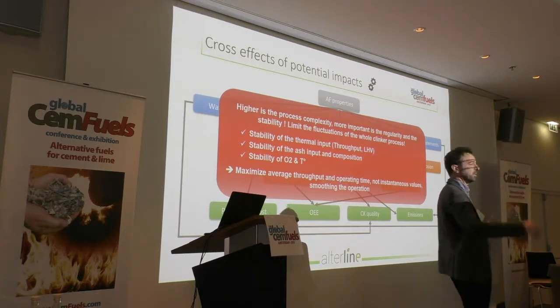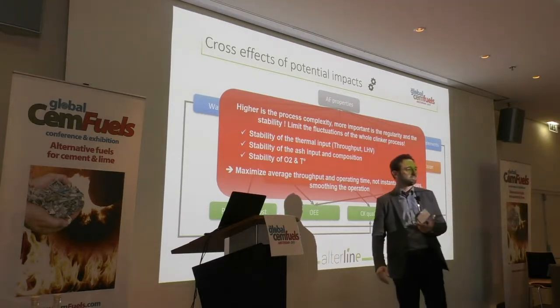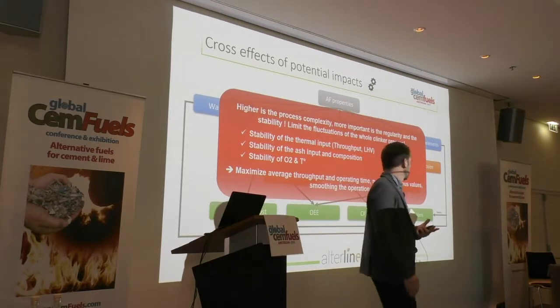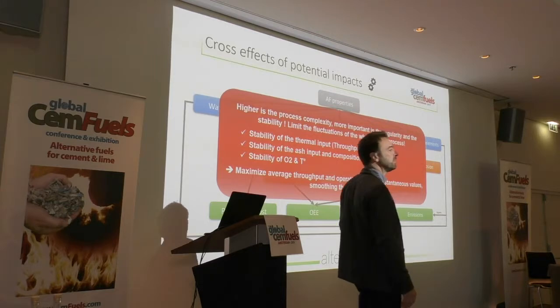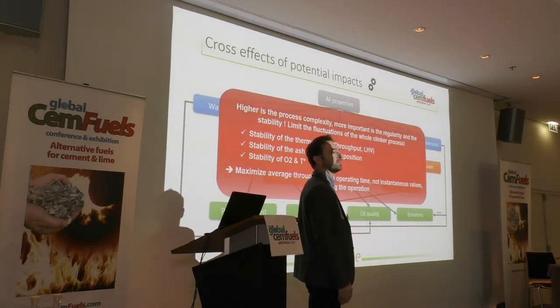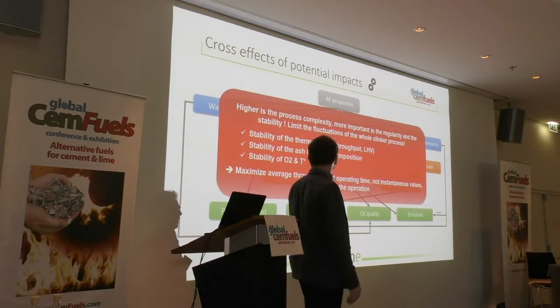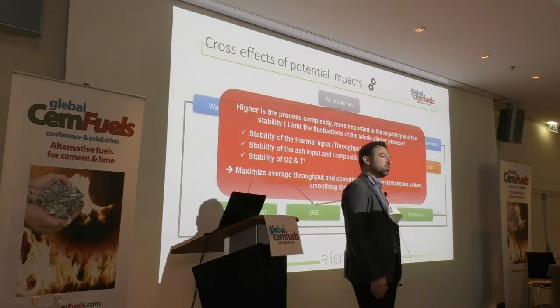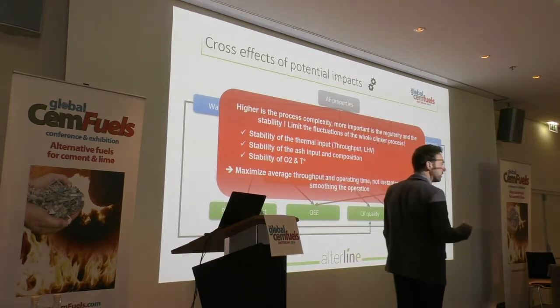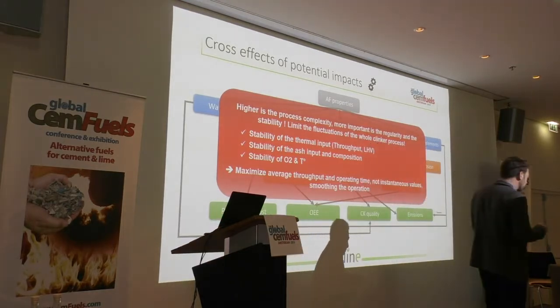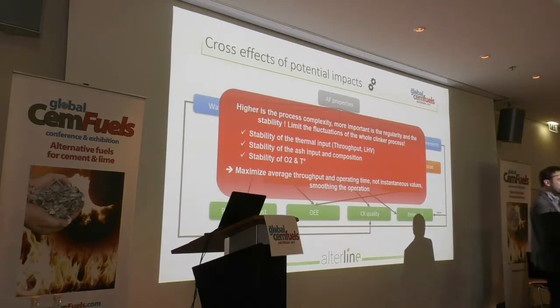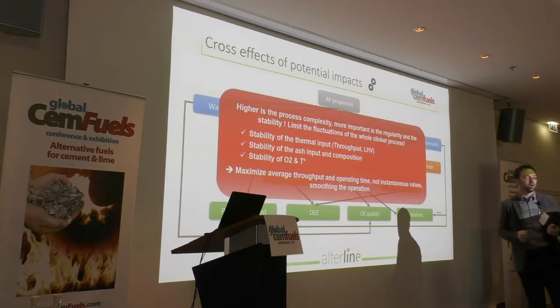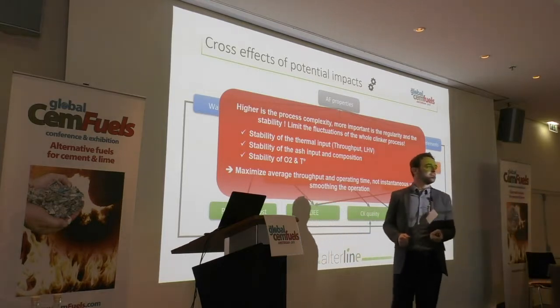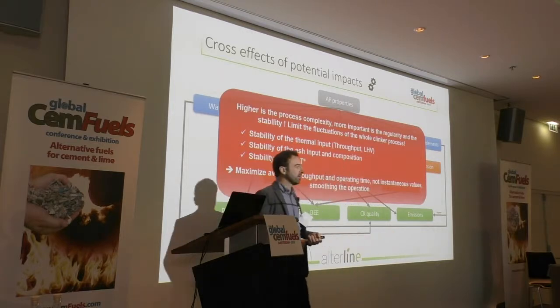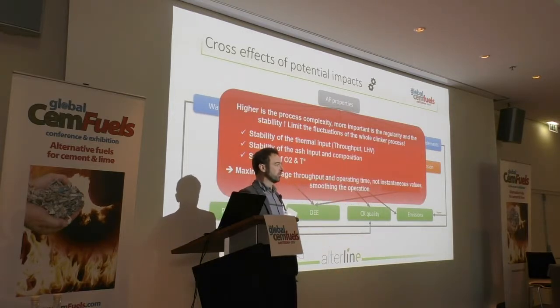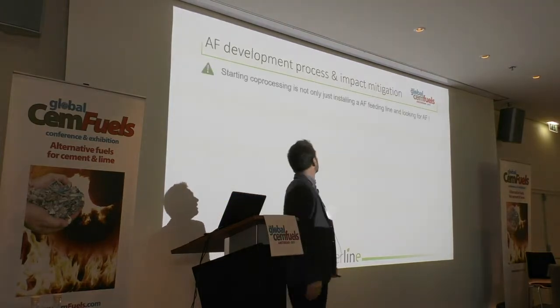If you are putting something like 0.05% ash on the clinker, you don't take it into consideration. And stability in both oxygen profile and temperature in the kiln. So it's always fighting against a trend in the operators, which is really challenging the throughput and going to the higher value during 5 minutes or during 1 hour. That's not the idea. The idea is to keep the installation available and to maximize the average throughput without too much fluctuations.